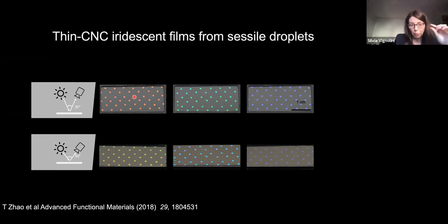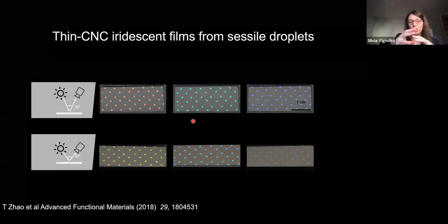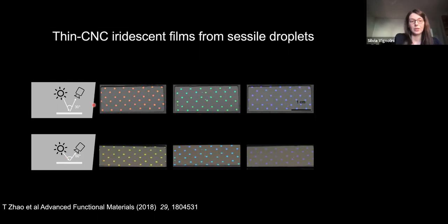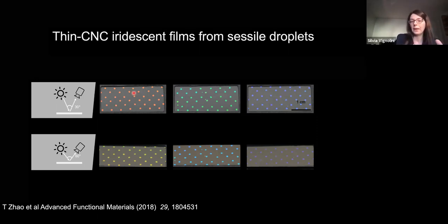And what is nice is that when you print this type of structure, as I was telling you, the structural color depends on the interaction between the light and the material. So if you change the direction in which you are looking at the material, if instead of looking from the top you look at more of an angle, the same printed macrofilm will change color. This effect is called iridescence. And this is actually what you see when you look at a metallized car. The platelets in a metallized car look metallized because they have this iridescent effect, so that the colors slightly change depending on the angle of incidence.